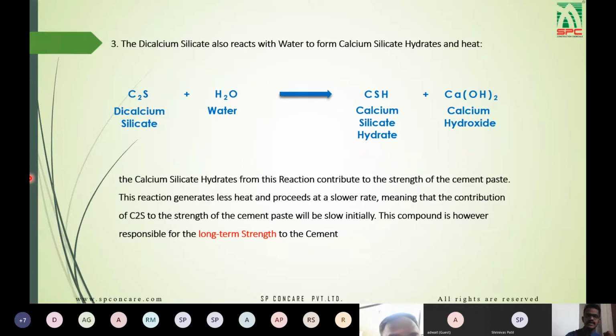This reaction generates less heat and proceeds at a slower rate, meaning that the contribution of C2S to the strength of the cement paste will be slow initially. This compound is, however, responsible for the long-term strength of the cement, or we can say the final strength of the cement.